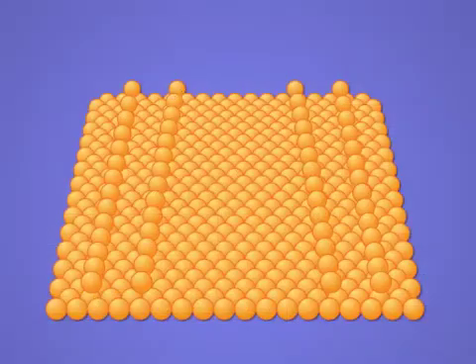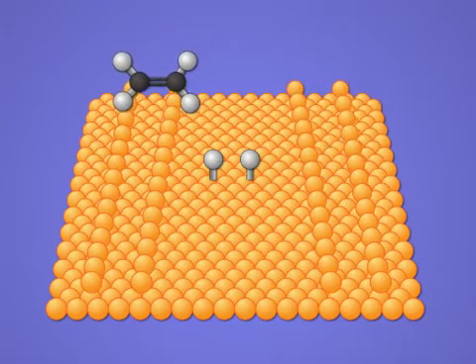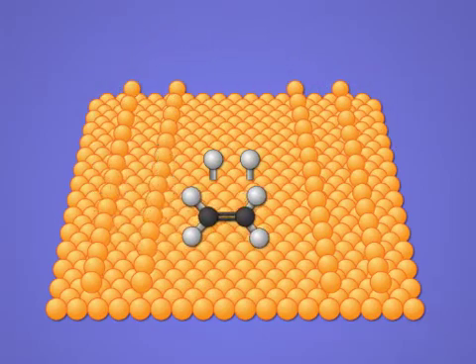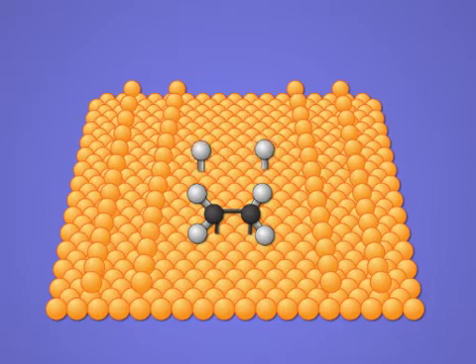This expression indicates that hydrogen adsorbs strongly to the catalyst, while ethylene adsorbs weakly. It is consistent with a kinetically controlled Langmuir-Hinshelwood mechanism.